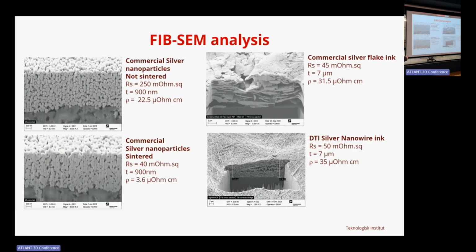One of the tools we have at our disposal is what we call FIB-SEM. This is just to look into different types of materials, for example, silver. We did this some time ago, silver nanoparticle inks, and this is before and after sintering steps. After we print, we bake it, but we just get rid of the solvents, so it's conductive, but not extremely conductive. Once we do a sintering step, which can be done with laser heat annealing or with photonic flash sintering, we can melt the particles together and get a much lower resistivity, in this case almost an order of magnitude better.